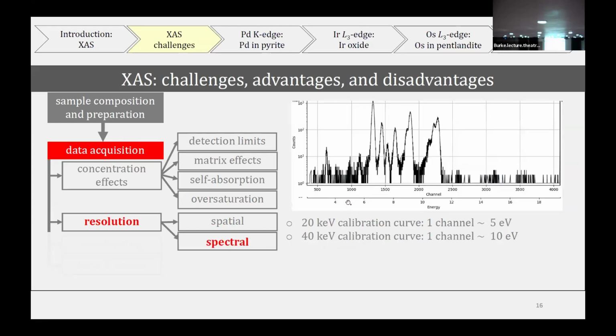And for spectral resolution, depending on the mode, people might understand this term differently, because when we are recording XAS, we need first to set the region of interest around the emission lines. So we see here this XRF spectrum, and these are the channels of the detector. And here is the calibration curve. Depending on the calibration curve we choose, for example 10, 20, 40 keV, of course a channel will contain a different amount of energy in eV. So we'll have different resolution spectra.